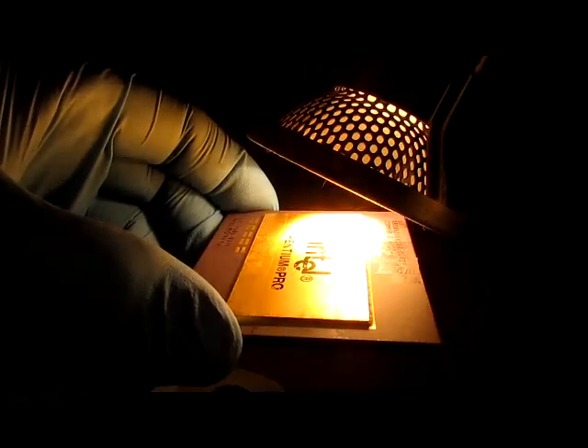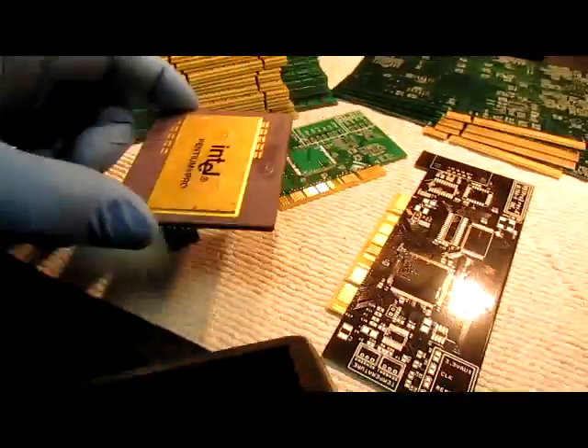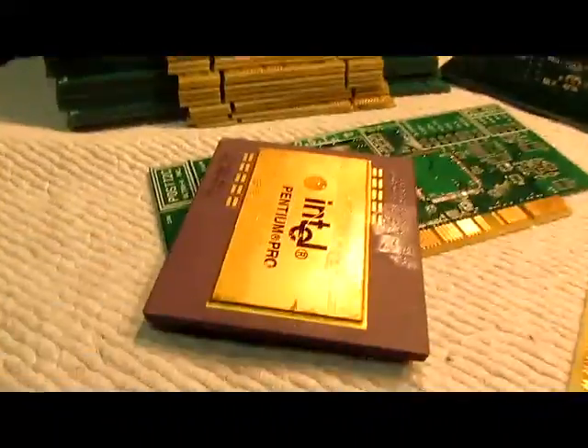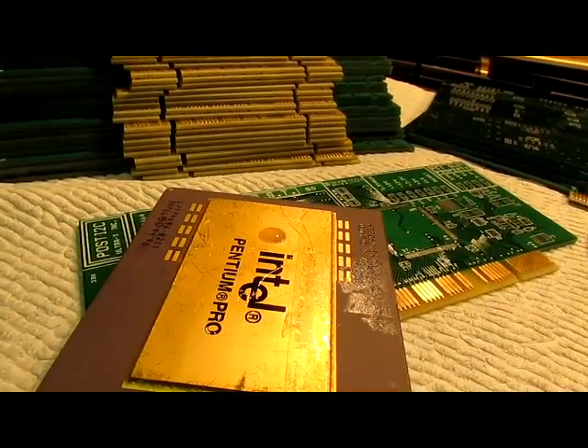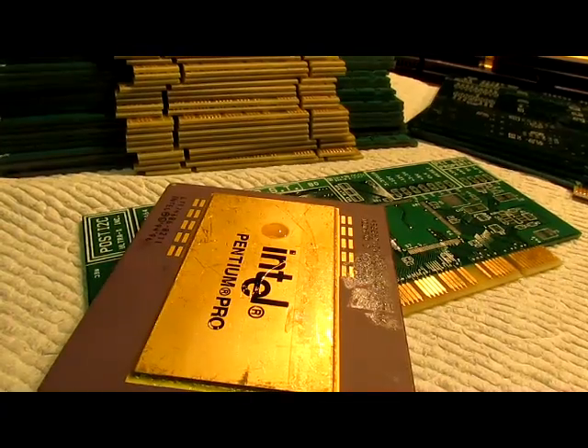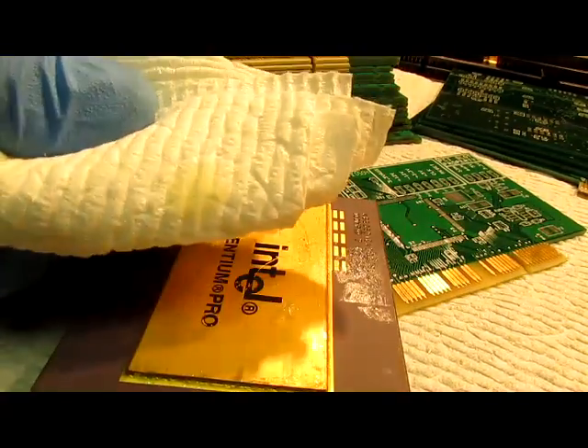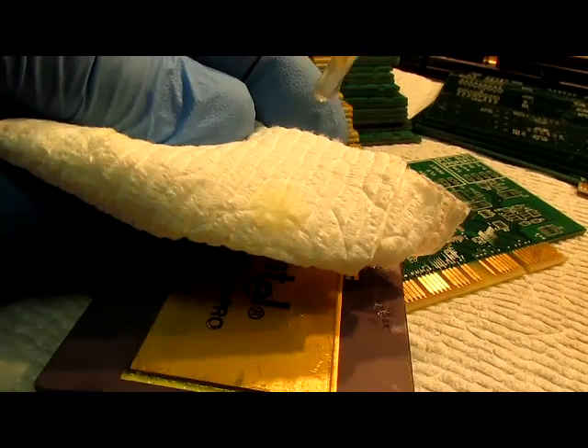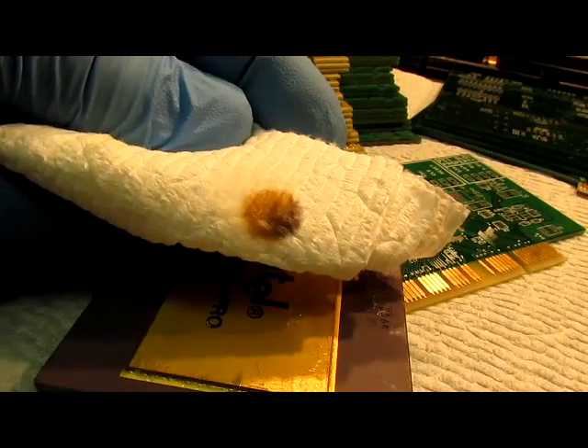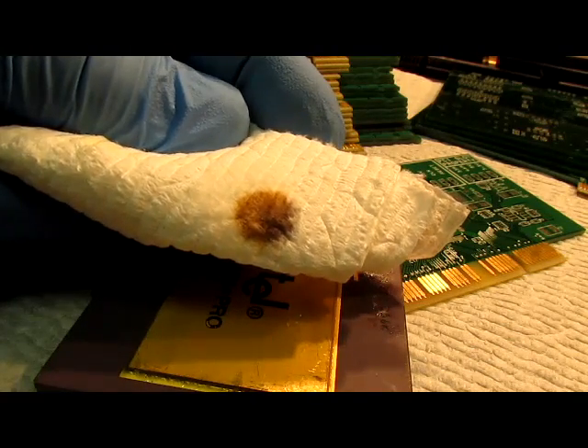It's been up by the light for about a minute now. I'll go ahead and bring it back down and do the test. I'll go ahead and blot it on a piece of paper towel — I can see a yellowish color. And I'll go ahead and add some stannous chloride, and that brown stain indicates that we do have gold going into solution.